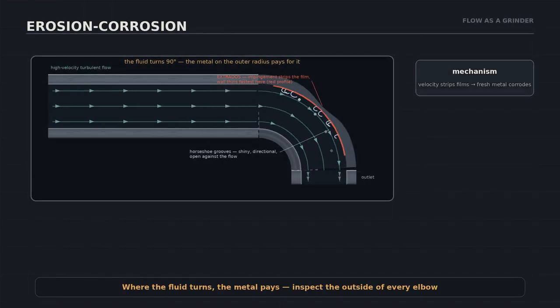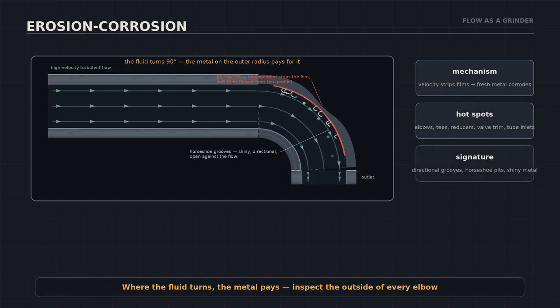Erosion corrosion is flow acting as a grinder. When velocity gets high, the moving fluid strips away the protective film faster than it can reform. Fresh metal corrodes, gets stripped, corrodes again. It concentrates where the flow changes direction: elbows, T's, reducers, valve trim, tube inlets. The signature is directional, horseshoe-shaped grooves of bright, clean metal. Counter it with lower velocities, gentler geometry, or harder alloys, and inspect the outside of every elbow.